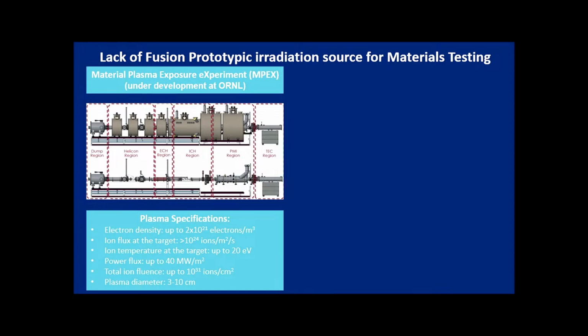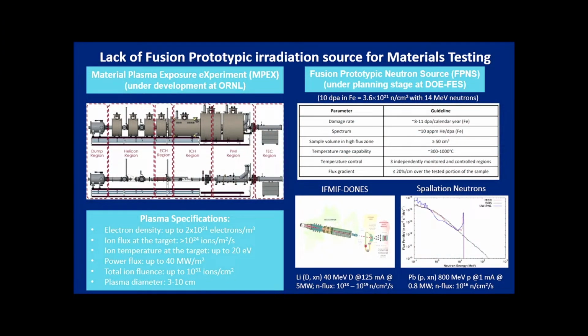That's the basic challenge on the materials side, but there is also a challenge on the materials testing side. We don't have anything available to do fusion-prototypic testing, even if we do have materials. There is a facility under development at Oak Ridge for close to five to ten years and still ongoing. This is going to test the plasma-phase material, thermal testing, particle testing. But there are no neutrons, no radiation damage part of it. For the radiation damage facility, DOE is trying to propose a fusion prototypic neutron source. This is still on paper. Even if we make a decision, it is a decade away. So we have a long way to go in terms of materials testing.